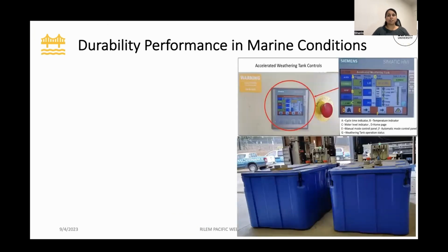To understand the durability or the performance of these particular composites in marine conditions, we used accelerated weathering tanks. As you can see, two very big tanks of 2000 liter plus water capacity are used. And we have used automated accelerated weathering tank controls, which can control the cycle time, the temperature, the water level, and it also indicates the moisture content and the evaporation inside the